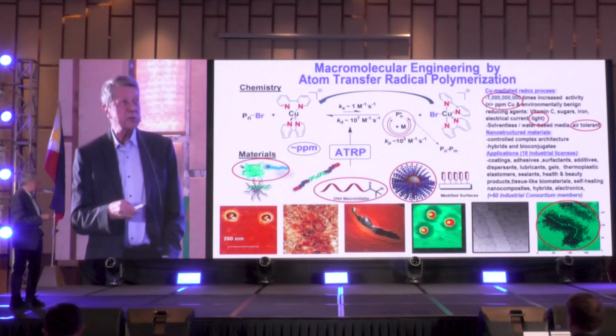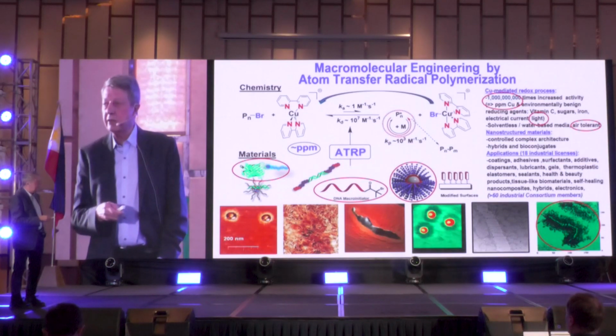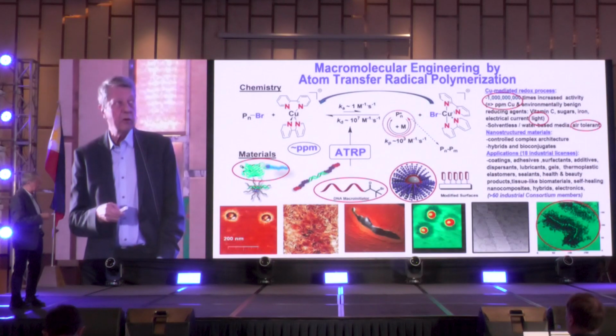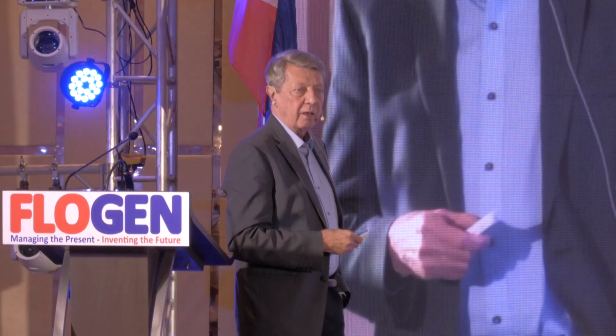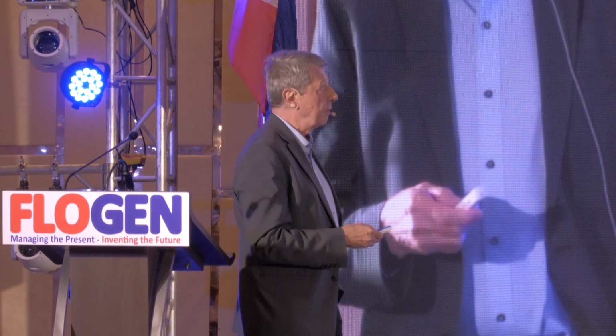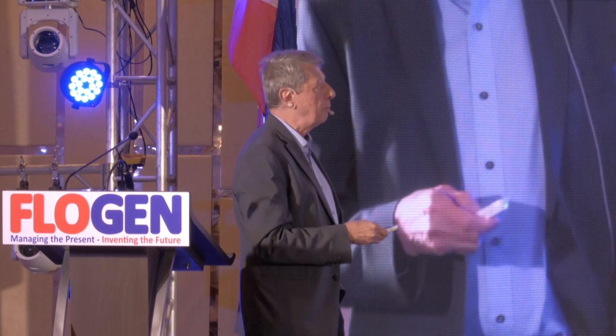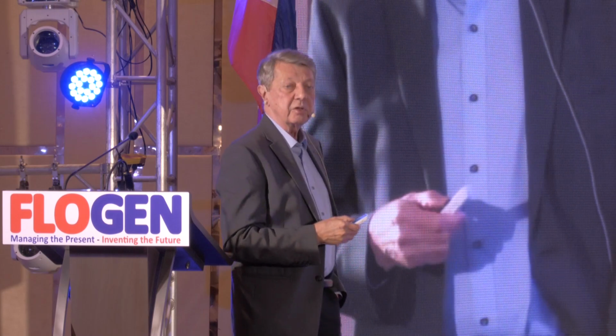Activator is responsible for making radicals. Deactivators, after 1 millisecond of activity, go back to a dormant state. So we developed catalysts which are now 1 billion times more active than originally used. So we can use them at very low concentration under green chemistry conditions, using parts per million of copper.